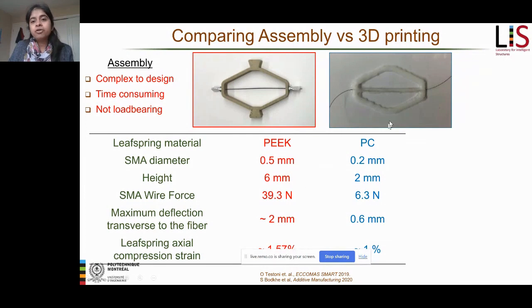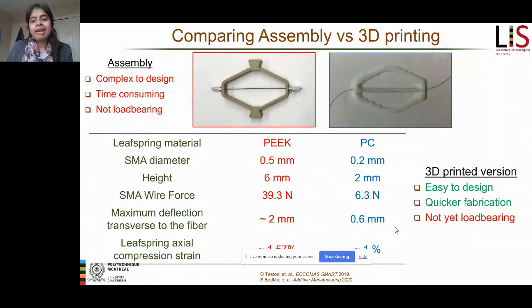We did have to go with a smaller SMA wire size because we needed the wire to really bend and not be too stiff to recoil during the printing process. That's why we had a smaller SMA. But if you see the strain percentage of the two structures that we made, it's quite similar, and we think that we can achieve similar strains with the 3D printed approach. So it was easy to design, it was quick to fabricate, and still we were not yet load bearing. So we're looking for something that can be much stronger.